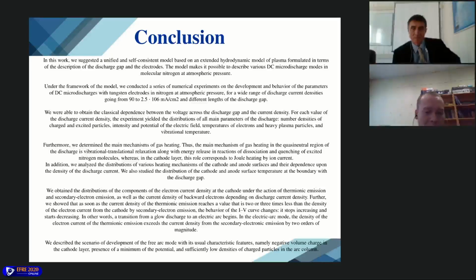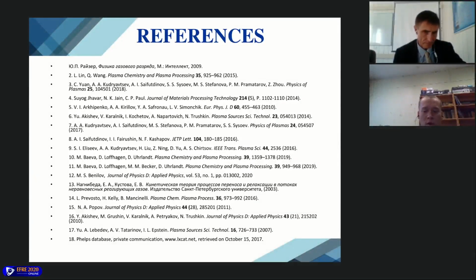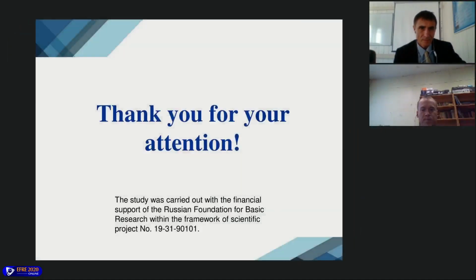And also we describe the scenario of development of the free arc mode, arc discharge, free cathode region. Its usual characteristic features, namely negative volume charge, the cathode layer presents a minimum of potential and sufficiently low density of charged particles in the arc core. Here are some references of our work. Thank you for your attention.